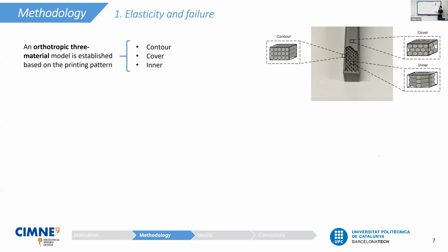So regarding the elasticity and failure, in order to characterize this material, we establish a modelization of its constitutive behavior. It is generally known that additive manufacturing components, since they are built layer by layer, show orthotropic constitutive behavior. However, we go one step further and we modelize every single printing pattern present in a fused filament fabrication component as an orthotropic material by itself.